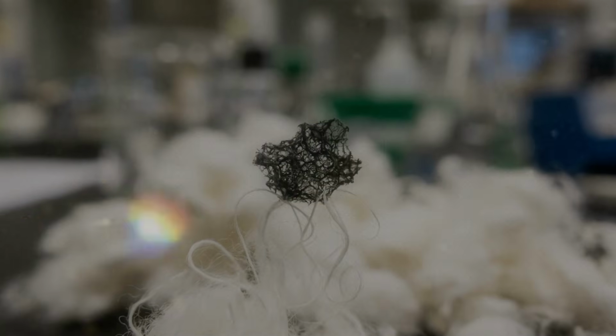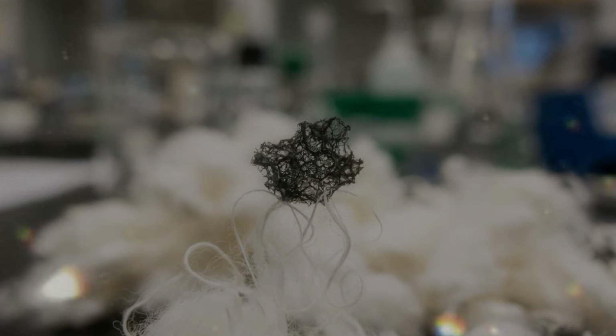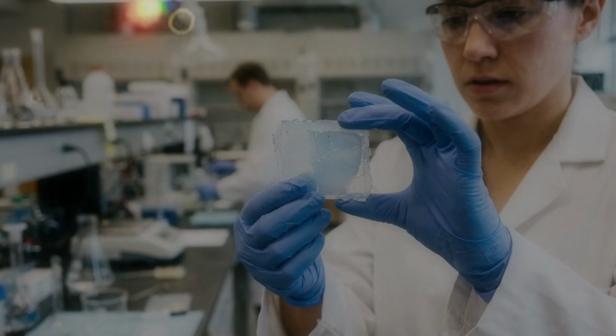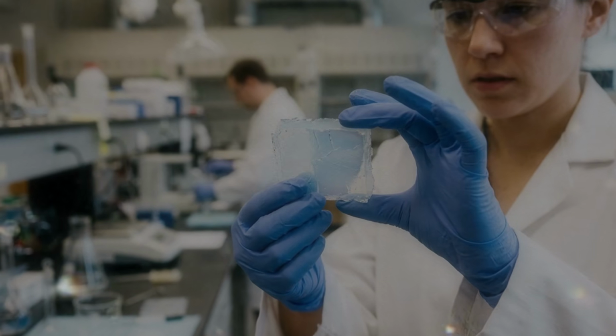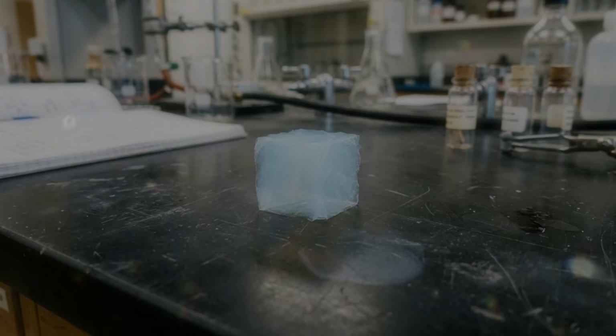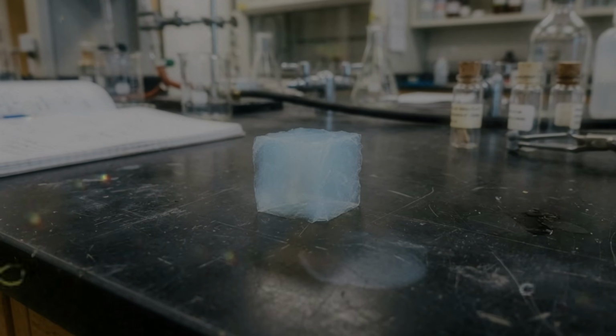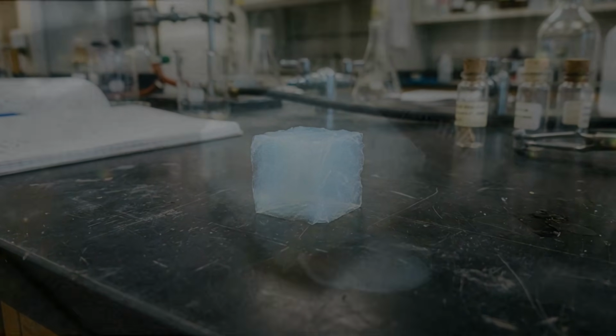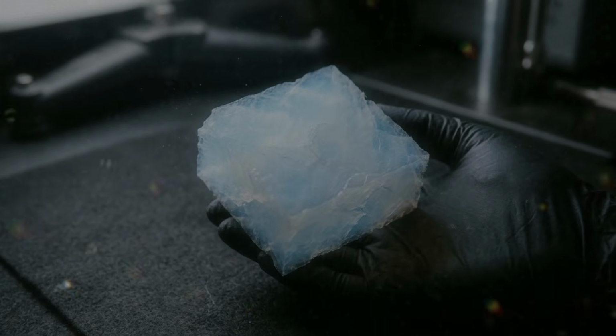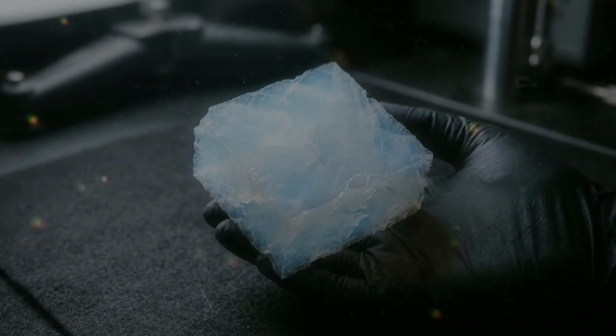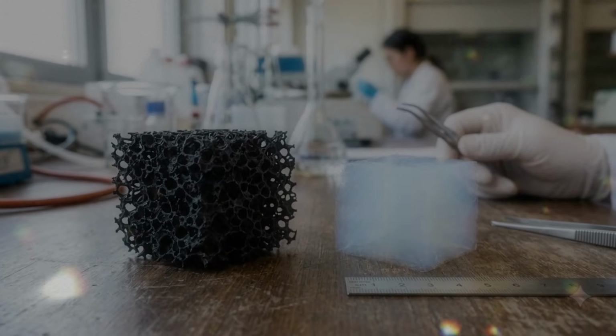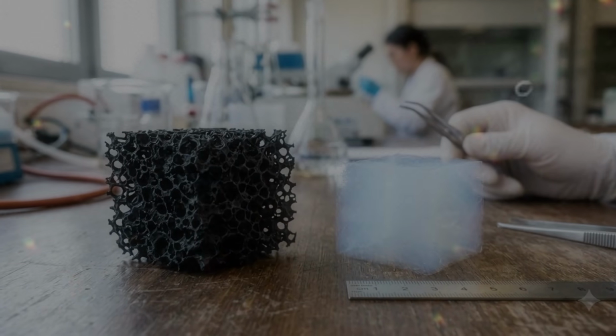Electricity follows a different route. Gas-filled pores do not normally carry current well. The electrical path lies mainly through the solid carbon network. For that path to work, graphene sheets, carbon particles, or nanotubes must touch one another from one side of the material to the other. A silica aerogel is usually a poor electrical conductor. Its structure can insulate against electrical current just as it insulates against heat. This is useful when the material must protect equipment without creating unwanted electrical connections.